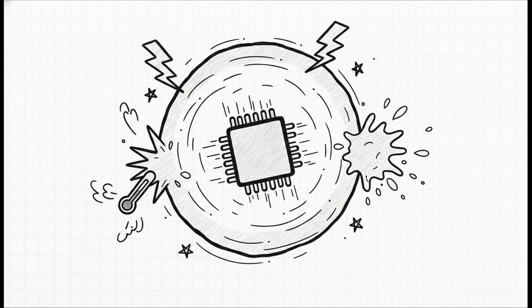On top of that, it acts as a phenomenal chemical diffusion barrier. When engineers try to dope the silicon with elements like boron, phosphorus, or arsenic to tweak its electrical properties, the silicon dioxide blocks them completely. That's what allows for ultra-precise circuit drawing. Plus, it has a massive 8-electron-volt band gap, making it a near-perfect electrical insulator.